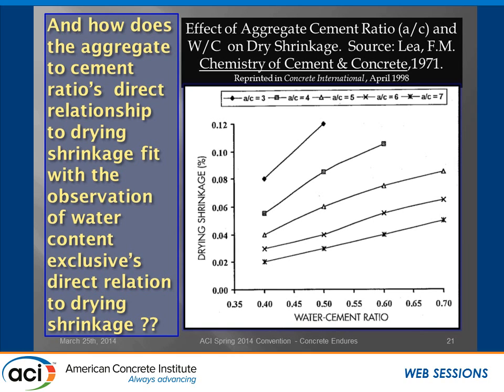That top graph, here's a 10-sack mix, 0.08 water cement ratio 0.4, 9-sack mix, water cement ratio 0.5. Go over here, that's roughly the same. You've got a 7-sack mix or 8-sack mix, and you can see here it doesn't really matter. It fits right in with that other phenomena we were looking at. You can go down to the bottom and do the same thing. You can draw a line at 0.04, and that's a 7-sack or an 8-sack mix, 6 and 5. So that gives us a better understanding of what's going on with shrinkage.